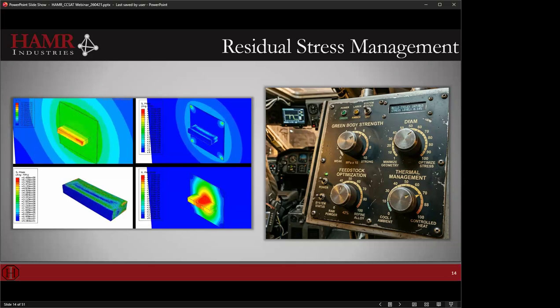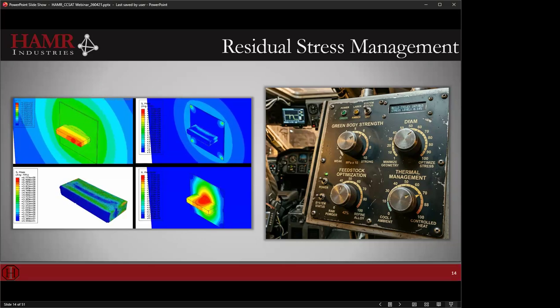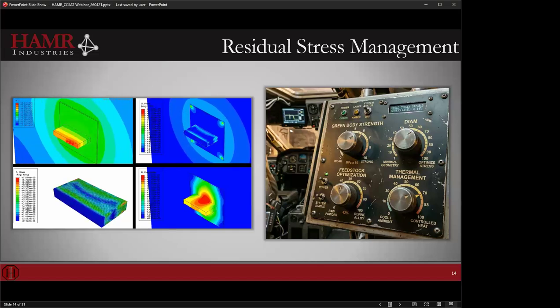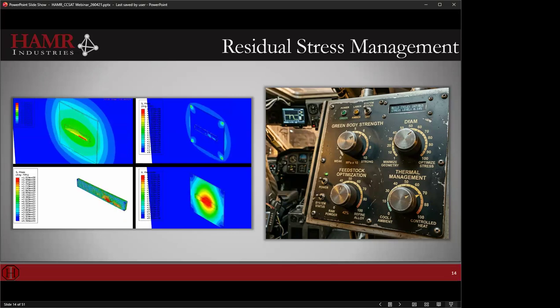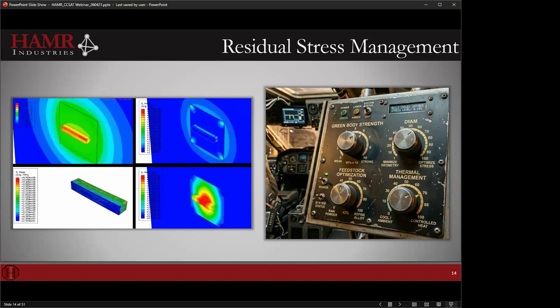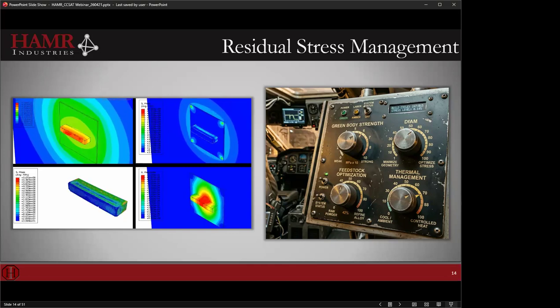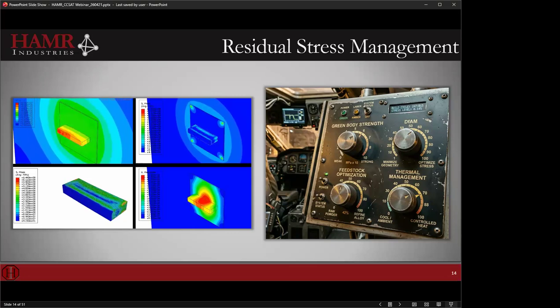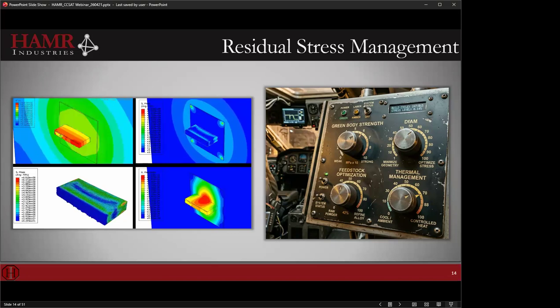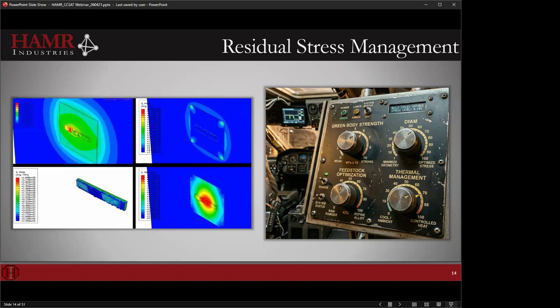So that takes us to the left, where we're working with collaborators. This work was funded in part by Army Research Lab, looking at simulating the full cold spray process. So here we're taking an actual tool path straight from the warp speed, and we're simulating the particle impact energy. We're simulating using CFD approximations, the convection heating from the nozzle, the convective cooling from the nozzle, convective cooling in the air, still air in the chamber, radiative conduction.